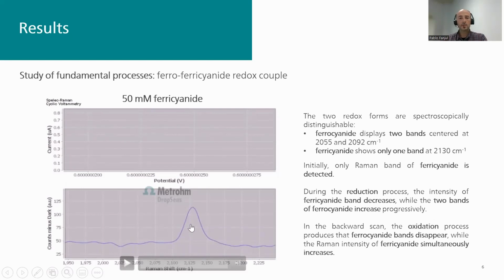And here in parallel, simultaneously and in real time, we will see the evolution of the Raman spectra. In fact, what we see in the Raman spectra is this band related to the cyanide bond linked initially to an iron 3 atom. So we will have only this Raman band. But during the reduction to iron 2, this cyanide band will be transformed into two different bands, because the cyanide presents different Raman spectra depending on whether it's linked to iron 3 or iron 2. And then in the backward scan, we will come back to the initial state.